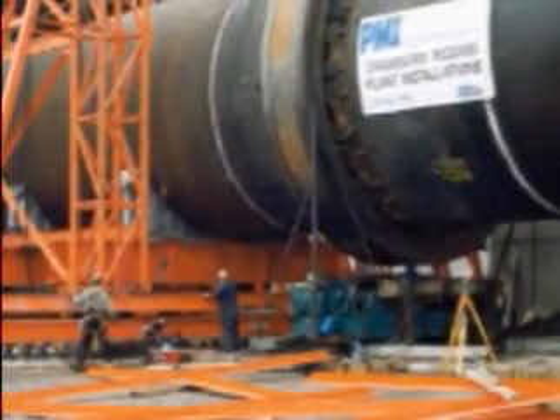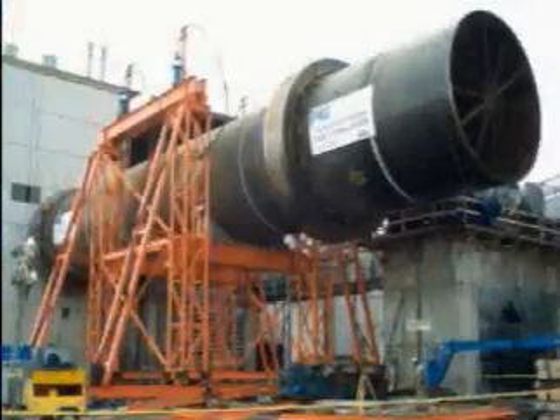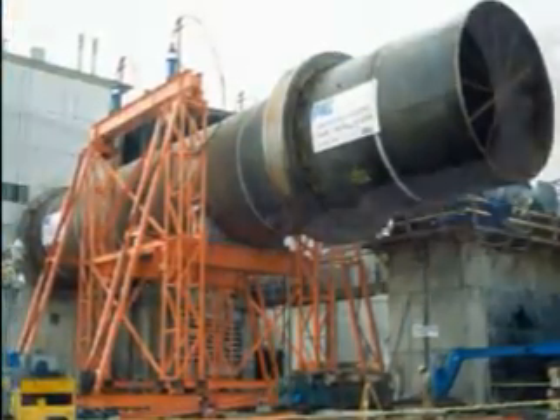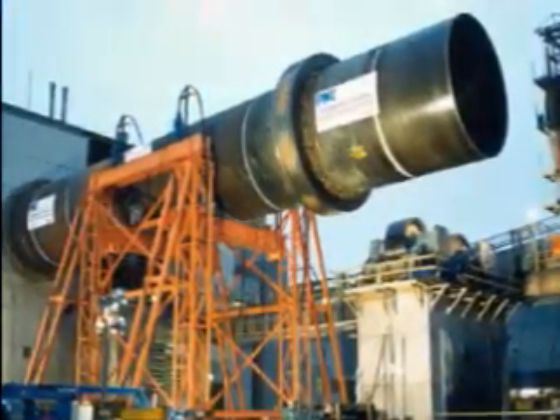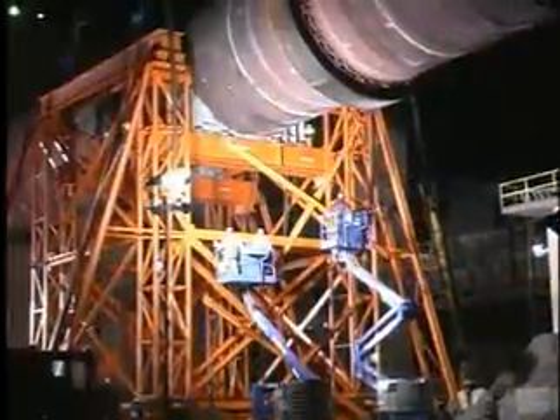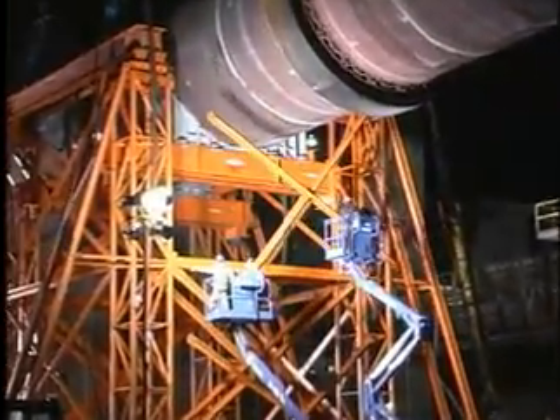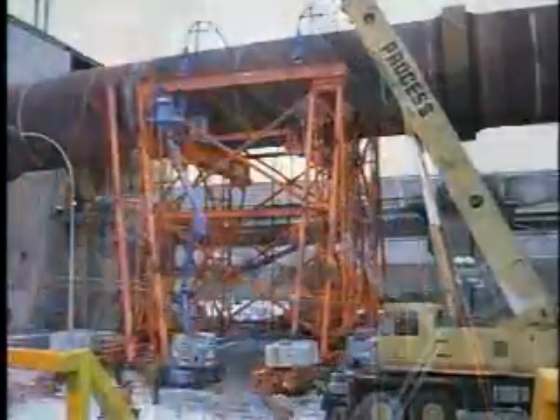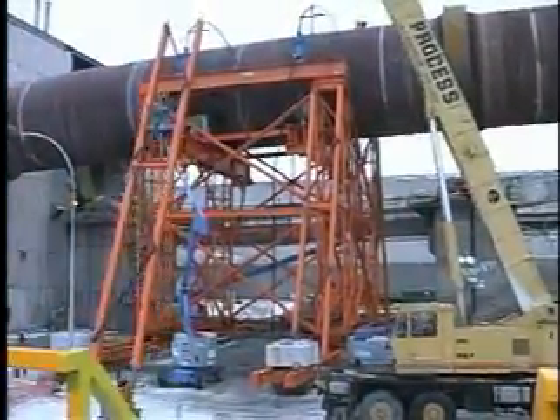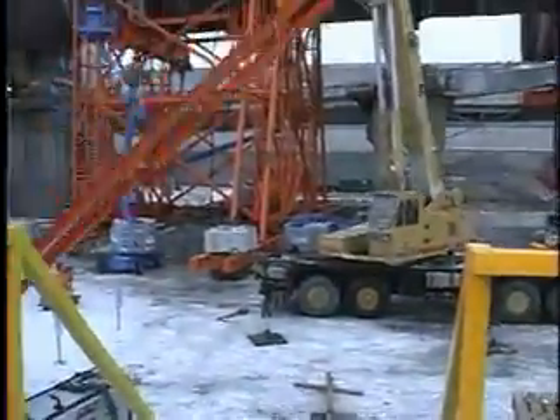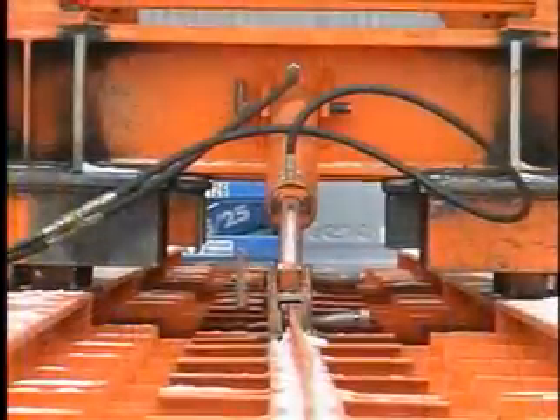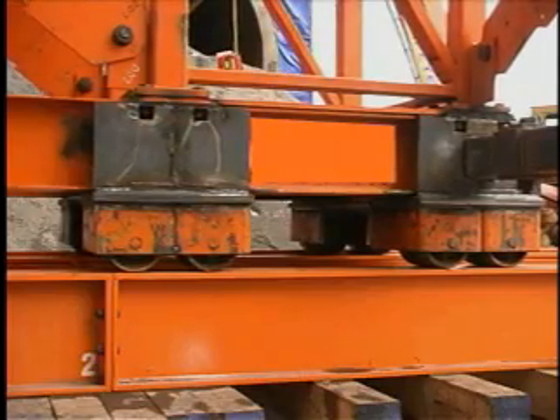There, the 130-foot-long kiln assembly was transferred to the lifting tower saddles and slowly raised by the 800-ton capacity strand jack system to a height of 50 feet, while tower cross bracing was sequentially installed below the load to stabilize the lifting tower system. The A-frame outriggers were removed from the lifting tower, and the tower leg propulsion jacks were again used to travel the assembly 35 feet along the track runway system, back to the pier and roller station location.